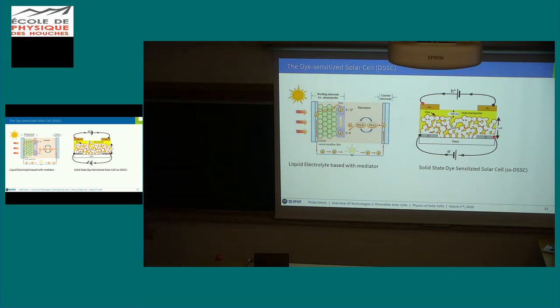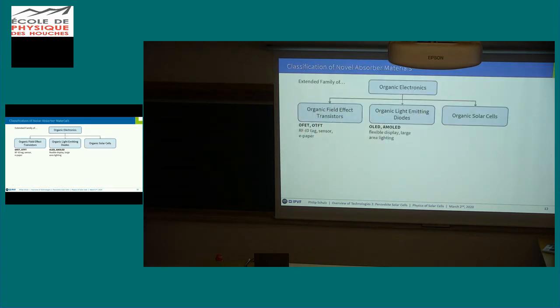Here you can see the dye around the titanium oxide particles. So sunlight is absorbed in the dye, electrons transport usually through the oxide nanocrystalline film, and then the hole transport through either the electrolyte or the solid state in the hole transport material.